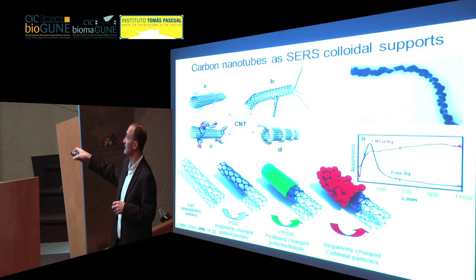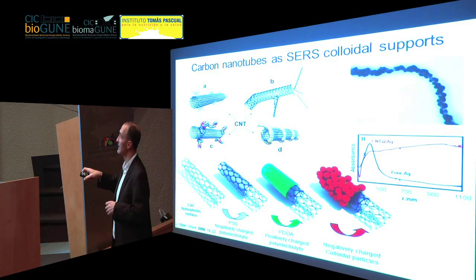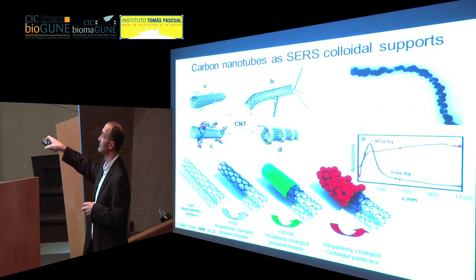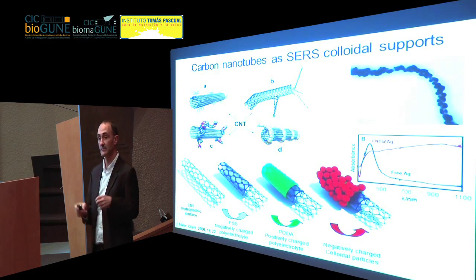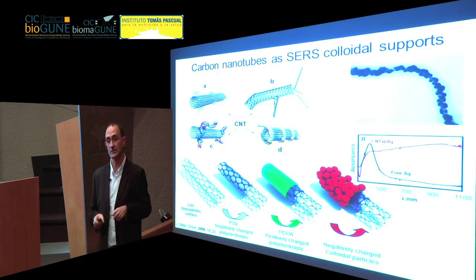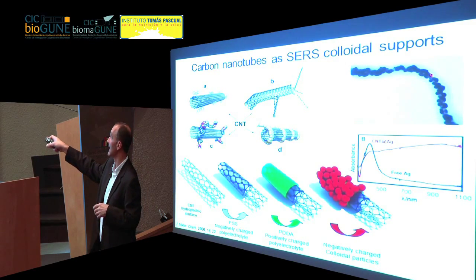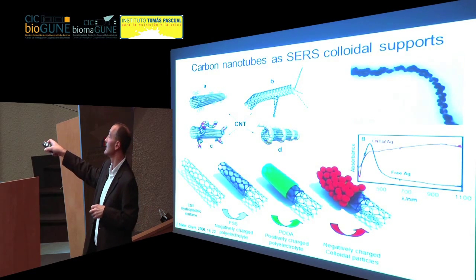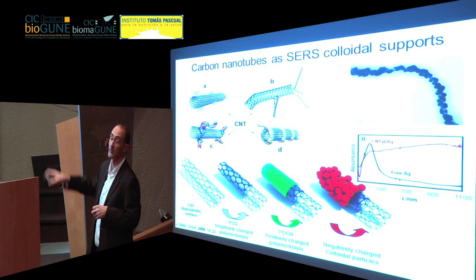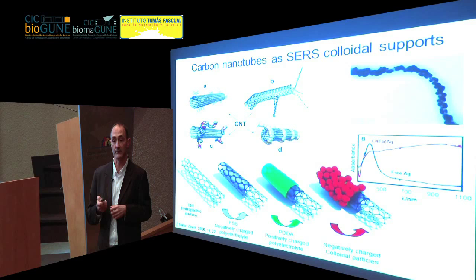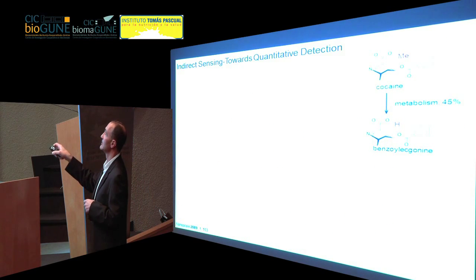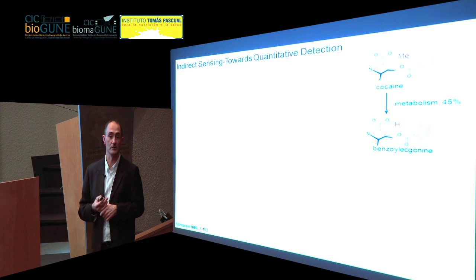So this is the change in the absorbance spectrum of individual silver nanoparticles and the silver nanoparticles on the carbon nanotube. It becomes much broader because of this coupling of the plasmons, so you're creating new plasmons at the gaps between the particles. So you can see here we have many gaps, and these are all places where the enhancement will be extremely high. So we decided to apply this for a detector for cocaine consumption.